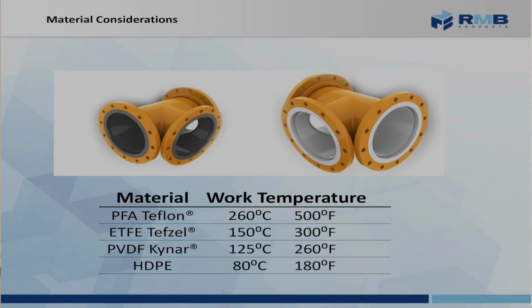So the materials that are typically used for rotational lining are ones that are available in rotational lining versions. So there are some resins that are more suitable and some that aren't. These are the ones that work well for rotational lining because they stick. Well, in the case of the bottom three, HDPE, Kynar, and Tefzel all are going to bond very, very well to the metal. And they actually offer versions that are good for rotational lining. Now, in the case of PFA Teflon, it does not stick well, and a primer is necessary to make sure that it adheres to the metal. But sometimes PFA or Teflon is the only choice for some applications because of the high temperature.